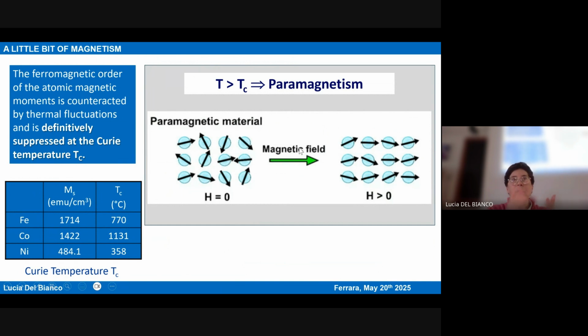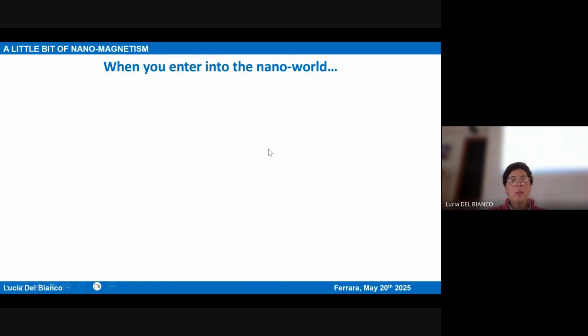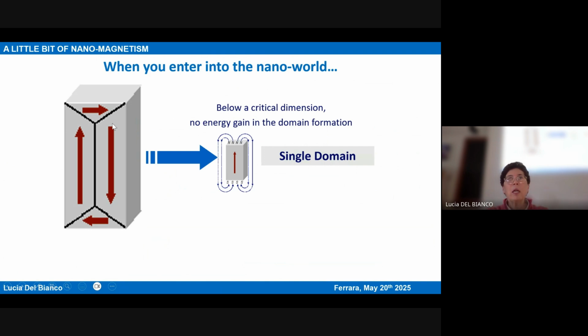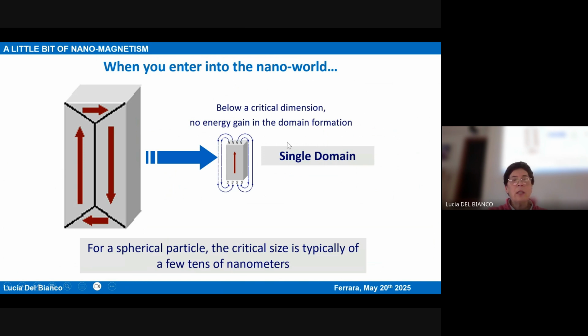And you can try to align again, at least partially, all the magnetic moments if you apply a very, very strong magnetic field. Okay? So what happens when you enter into the nano world, when you reduce the dimension of your ferromagnet to a nanometric size? The first thing that happens is that there is no more subdivision into magnetic domains, because of course, the subdivision into magnetic domains has a cost in terms of energy. And therefore, below a critical dimension, there is no energy gain in the domain formation. Therefore, if you have, for instance, a spherical particle, the critical size depends on the type of the material, but is typically of a few tens of nanometers. And therefore, a magnetic nanoparticle is a single domain, let's say.